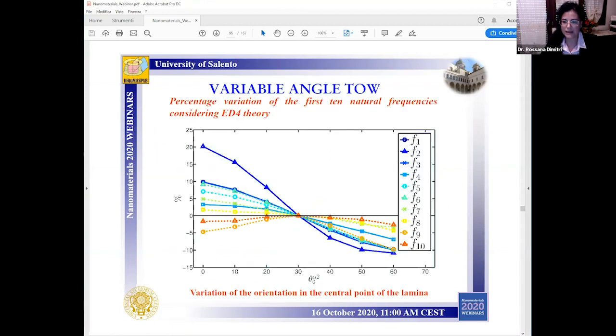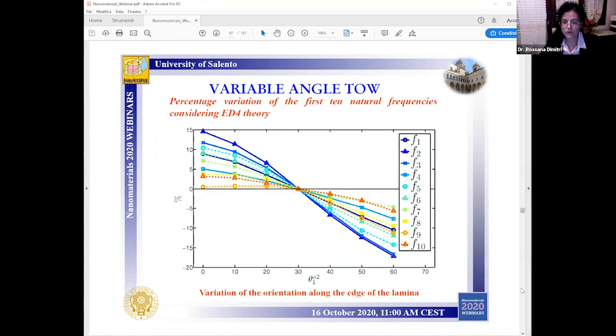And here in detail, look at these plots which show a clear variation in percentage of the natural frequencies with the variable orientation of the fibers in the central point of the lamina under a selected higher order theory. So note also that the first natural frequencies of the system are even more sensitive to the fiber orientation than the other ones. This behavior is also confirmed in these other plots, where we analyze the influence on each natural frequency of a varying orientation of the reinforcing phase along the edge of the lamina.